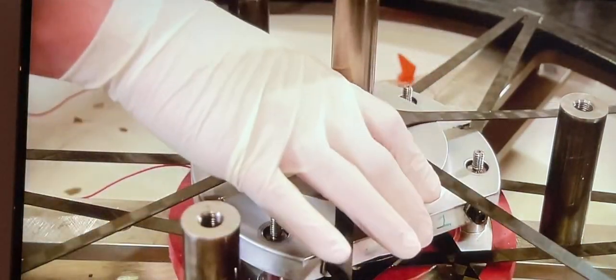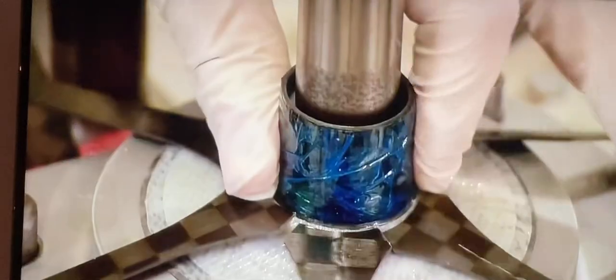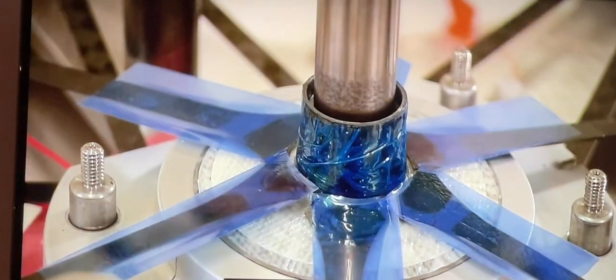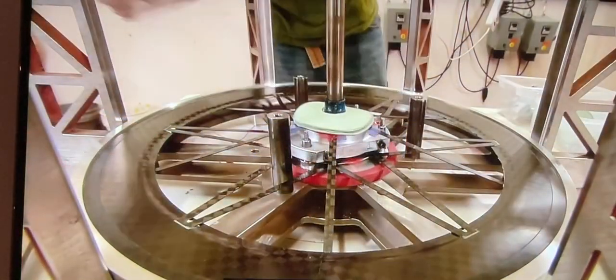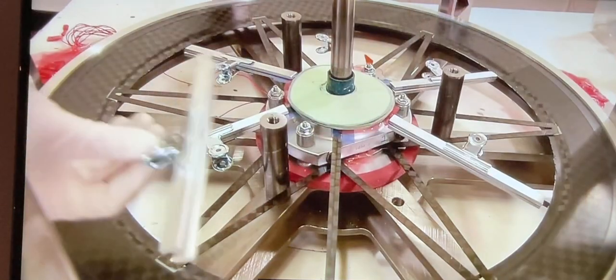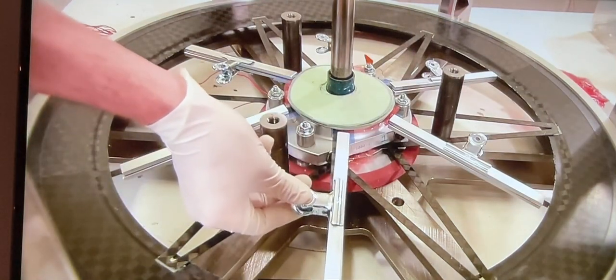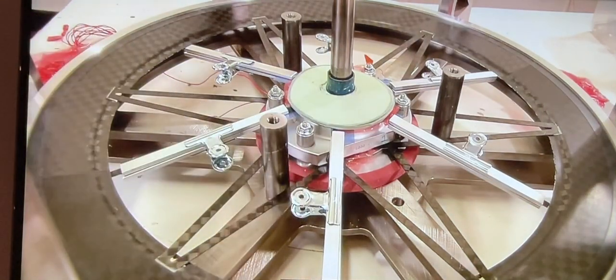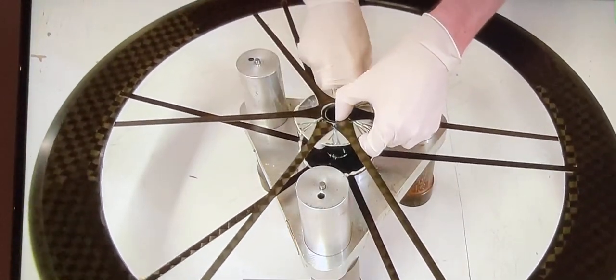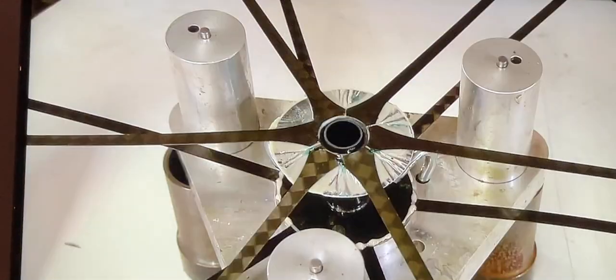He places a metal spacer between the 2 flanges for now and tapes the spokes to prevent adhesive from trickling down onto them during the heating process. He adds a piece of release film and a silicone pressure pad. He clips metal splints to the carbon fiber spokes to support them through the cure. And with the spokes now pressure bonded to the flanges, it's time for fine-tuning.